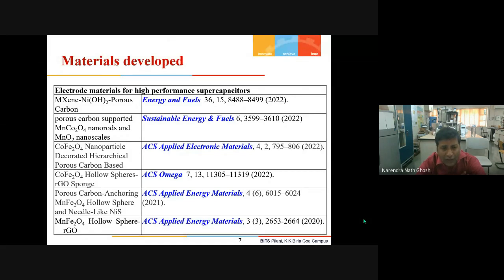So we have prepared this porous carbon from the coconut fiber. How it is transforming from coconut fiber to porous carbon, I will show you. Then we have incorporated the manganese cobalt nanorods and manganese oxide scale-like structure within the porous carbon support.